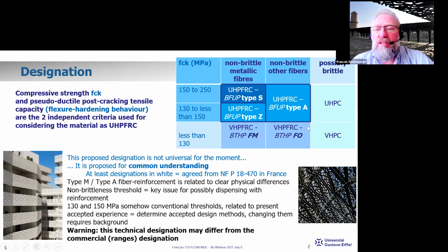In this block, we will speak of UHPFRC because the compressive strength is high enough, and this is the sign of high enough durability, and we have the flexure hardening behavior that makes it possible to use it for structures. If we have a lower strength, it may be very interesting for other projects, but the durability and compressive strength are lower, and we call it very high performance fiber reinforced concrete, with a V.